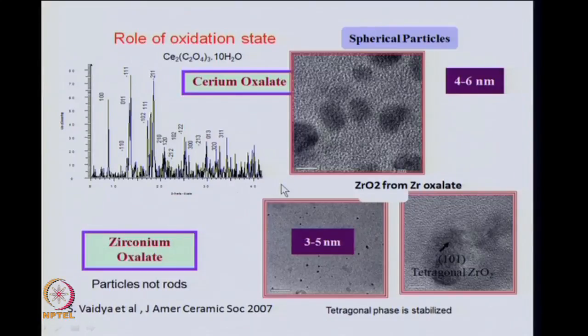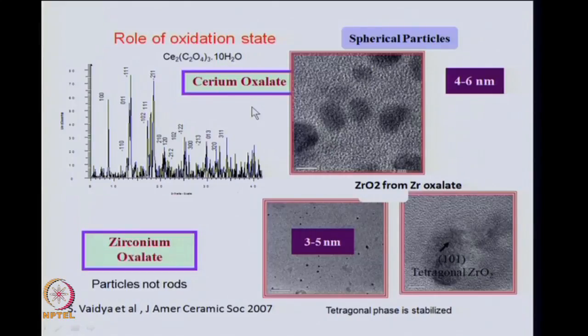So, it appears that when the oxalate ion is negative and the metal ion is dipositive, with the same charge magnitude but opposite, then it forms anisotropic nanorods in CTAB based microemulsions, whereas when the oxidation state is larger, say 3 or 4, then they give rise to spherical particles of cerium oxalate and zirconium oxalate. Of course, they again can be decomposed to give you zirconia or ceria depending on the conditions. And in this case, we stabilized a tetragonal ZrO2 phase, which normally is stable only under certain conditions. So, you can make metastable phases using the microemulsion process.